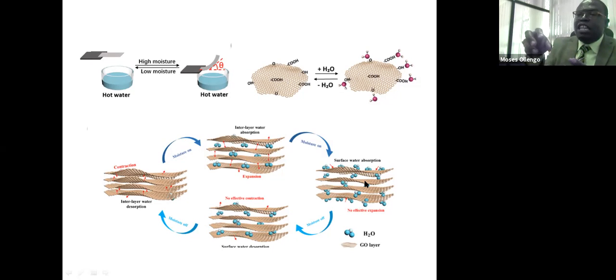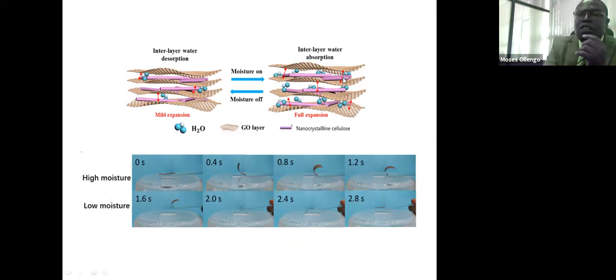And so when we bring in the NCC into this, we are introducing some form of binding, some form of higher-level moisture sensing, because these are two materials that are very good with moisture. But we are also introducing a bilayer effect, and therefore there is a charge residence on either side. In this case, we are binding them, so there's likely to be a more elongated, higher stiffness, and we are not likely to break. So the sheets are likely to give more promising work along the way. That's why we introduce those rods in there, and those rods are interconnected by van der Waals forces and the glycosidic bonds, as I showed earlier.